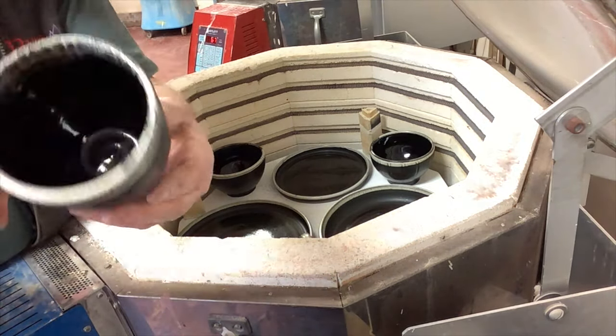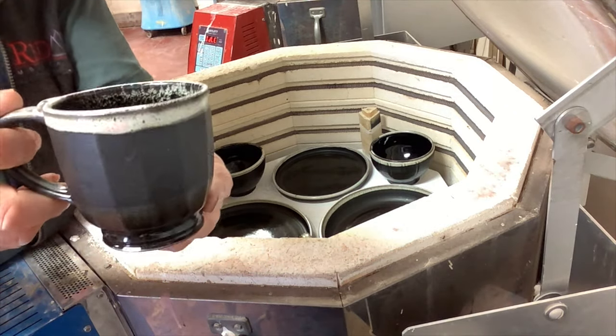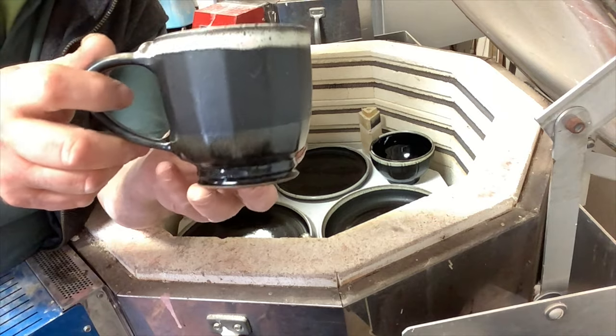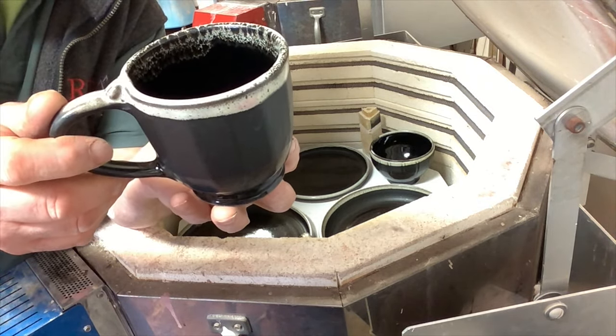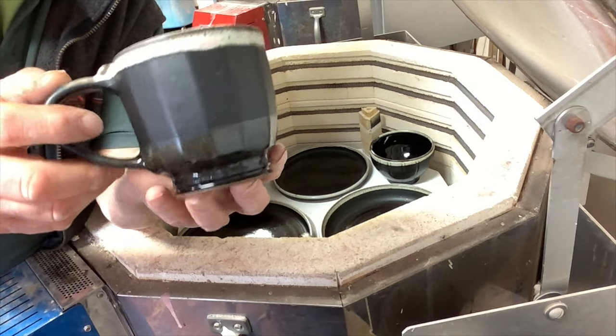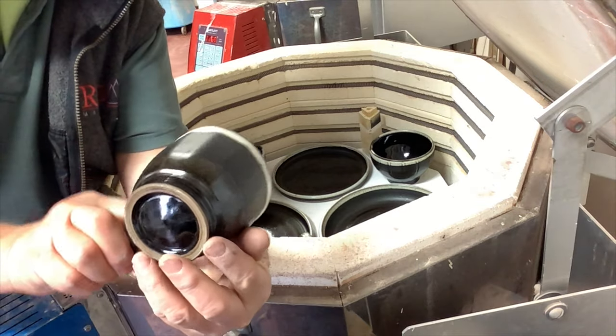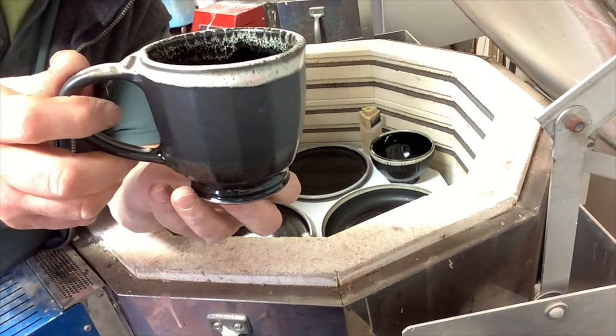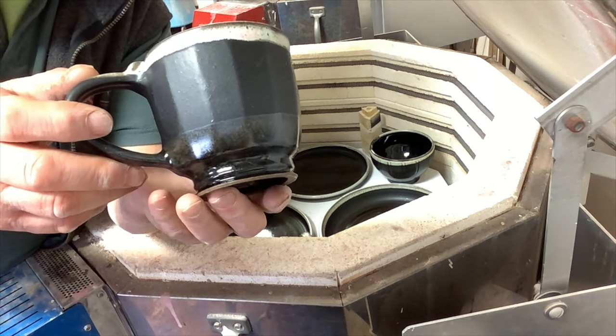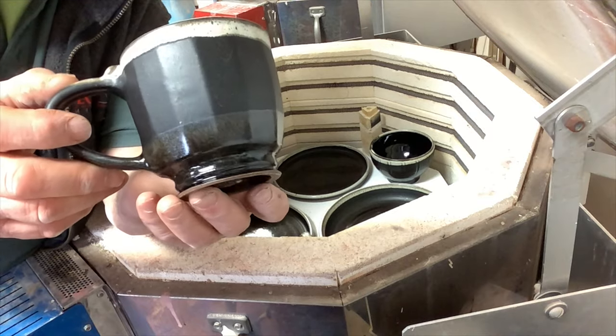They're kind of a, I would say, teacup. Or mug, I guess you could say, but look at the oatmeal. Very nice. Oh, there's a little pink there too. Chrome tin pink getting in there somehow. Not sure how that came in, but it'll only take one fleck of chrome or vapor of chrome in the kiln to make that tin in the actual oatmeal go a little pink.